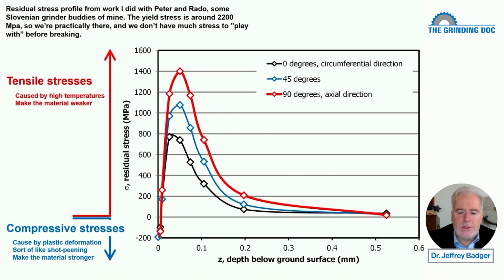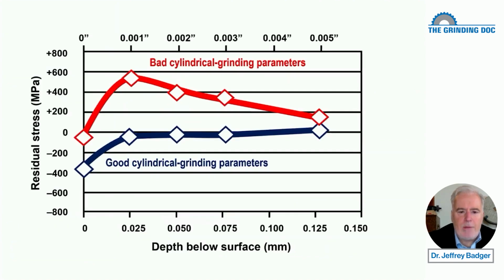So this was a company that called me up, and they said, hey, man, we've got a problem. We're making piston shafts, and our piston shafts are breaking. They're fine, they're not cracked, but we sent them into the field, and we put them in operation. And instead of lasting 10 years, they last a week, and then they crack. What's going on? They did a residual stress profile, and what they found was that they had residual tensile stresses up around 600 megapascals. That's kind of high. And they wanted to fix that.